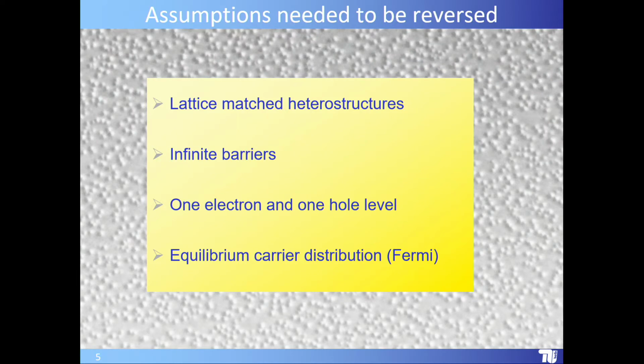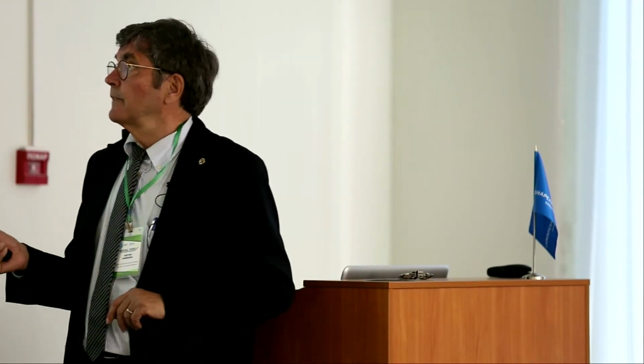Now, the assumptions which were put into all that theoretical work was you should use lattice-matched heterostructures. Most materials which you use today, most 3-5 materials or 2-6 materials, are indeed lattice-matched, but not all. The assumption was infinite barriers, something that doesn't exist in physics. One electron in one bound hole level only, and an equilibrium carrier distribution, which means a Fermi distribution. This proved to be an unsuccessful technology.